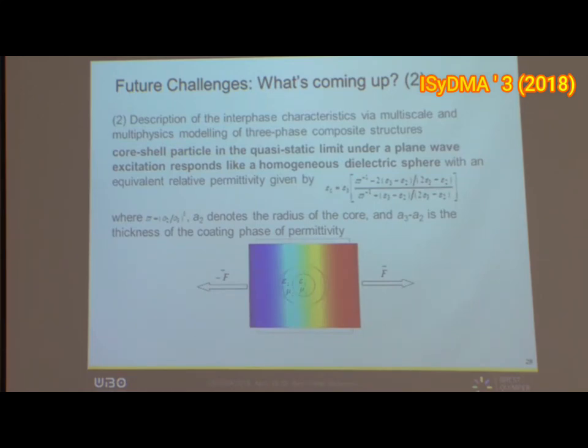Another more theoretical issue we are dealing with is to understand the role of the interfaces, because the interfaces are very complicated in the systems. We're trying to model using simple ideas, describing the interface as a specific phase with intermediate properties between the inclusion and the matrix. Using finite element simulations, we can access a lot of results, and we expect to have a theoretical understanding of what's going on at the interface between the polymer matrix and the graphene content in a few weeks or a few months.